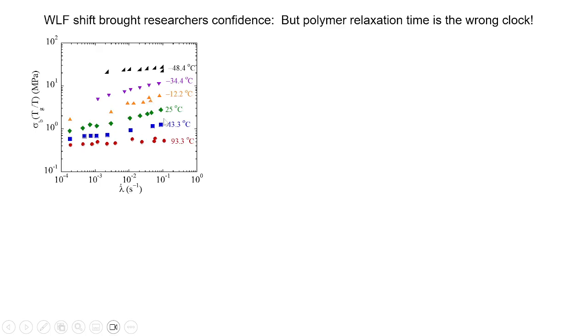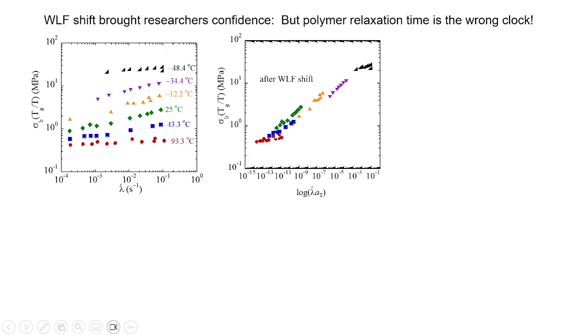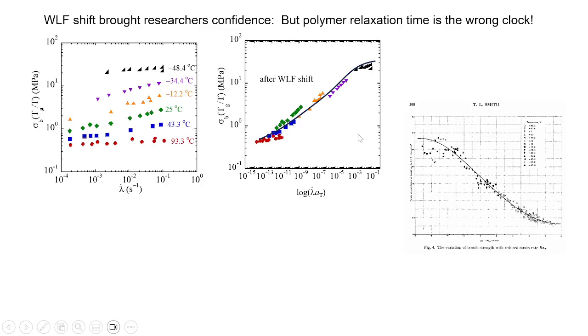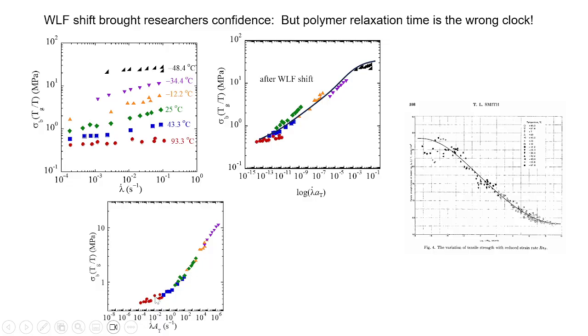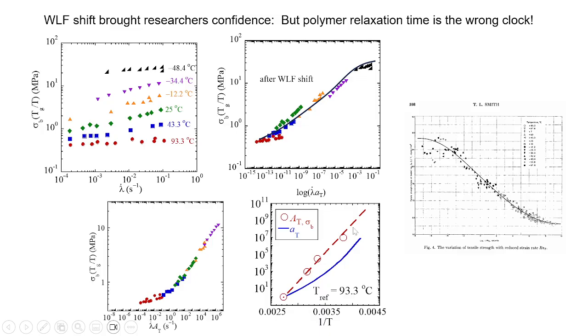And they said, oh, that's in the 50s. WLF was just discovered. Let's do a temperature superposition. Let's shift them. And they find if they use WLF, you get a curve almost like a master curve. That's published in all the literature. Except if you look a little carefully, if you try to really produce a master curve, you find you need a shift that's different than the WLF. Okay, that's the red shift. That gives you a much better master curve. And it suggests that temperature dependence is rather different than WLF.